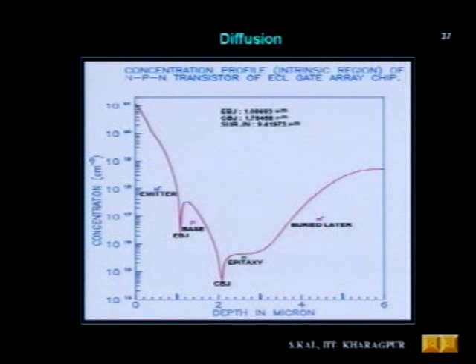Okay. And here is the emitter, you see the phosphorus, and have you observed some sort of kink here, a small portion here, it's not exactly smooth, so some kink has been observed here. Then this is the emitter base junction, then P base is here, then the collector base junction, then this is the N neutral epitaxial layer, and then the N plus buried layer, and then again you will get a junction. That junction is the buried layer to substrate junction, and that junction will be obtained at 9.42 micron depth, and this is up to 6 micron depth.